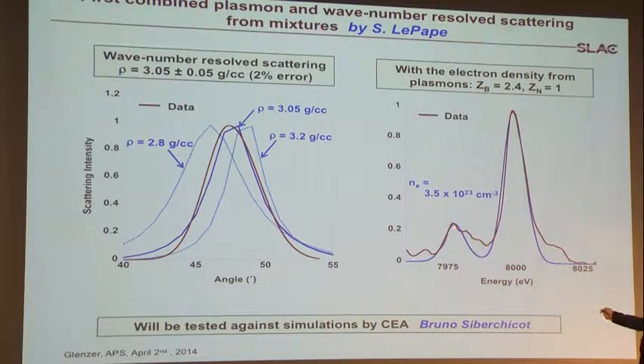Now we've also measured the plasmon. So the plasmon gives the electron density. So you have mass density, electron density, so you can derive ionization in shock compressed materials. And that's, of course, a new technique, and we are looking at particle simulation by CEA, who are performing the simulation as we speak.